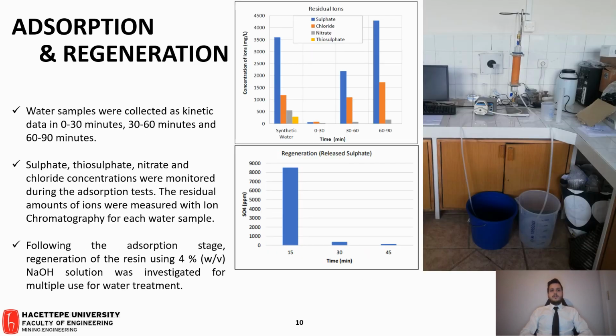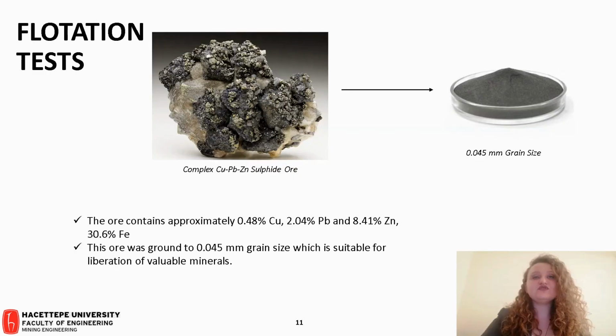As adsorption is a continuous process, after a certain time the resin was not able to capture all ions. As a result, the ion exchange reaction may occur in the reverse direction after 60 to 90 minutes. Results show that partial cleaning of water is possible and the resin can be regenerated and reused multiple times for water treatment. Flotation tests are the second part of our project.